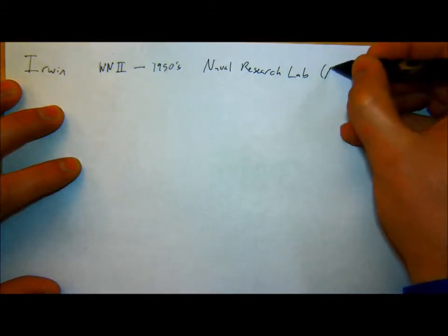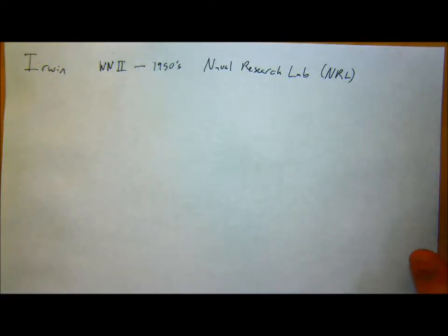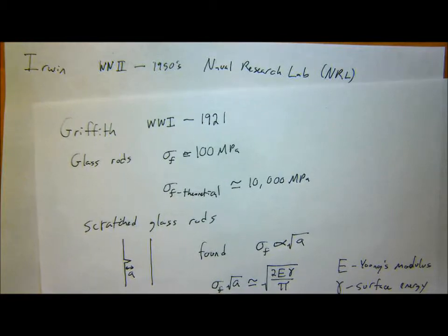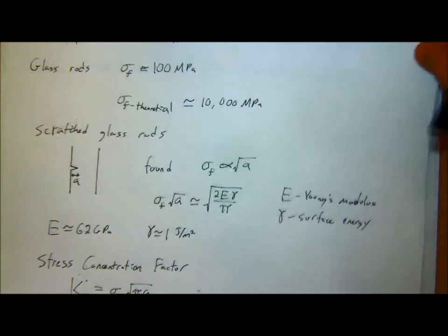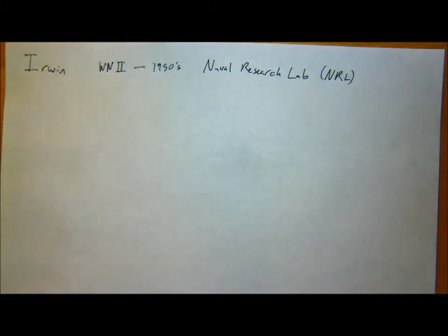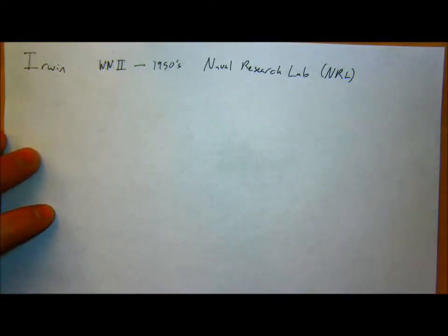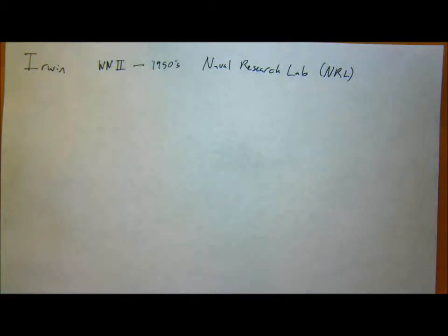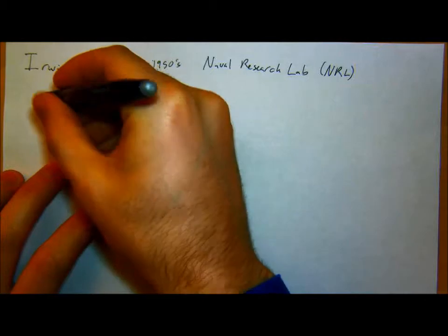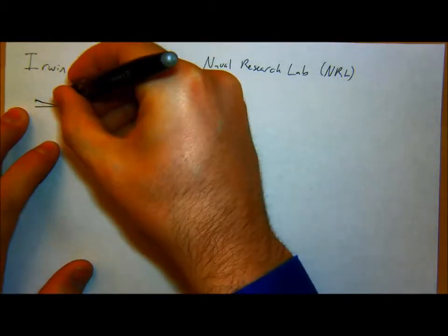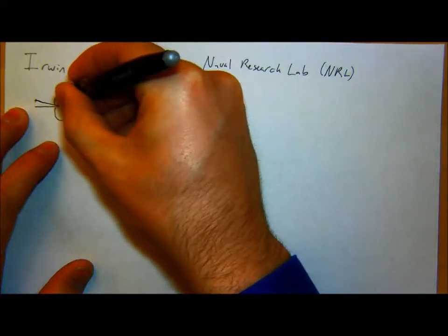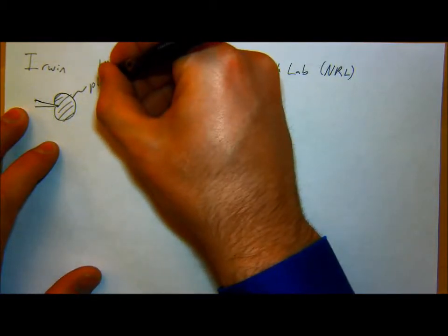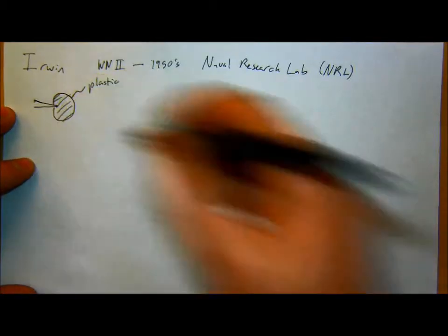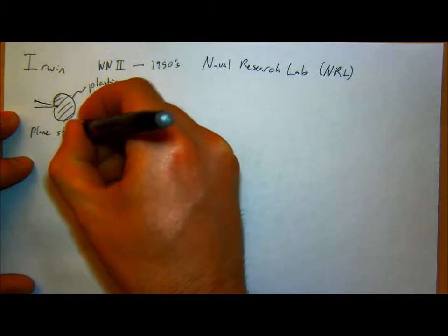Where Griffith was only thinking about glass rods, which are brittle materials, it turns out this relationship didn't really work as well when you tried to plug in values for things like metals or polymers, things that were ductile. So Irwin said, well, let's think about the plasticity around a crack tip. I know that I'm never going to get an atomically sharp crack in a material. Really, that crack is going to blunt out. So instead of just looking at the crack itself, I'm going to think about the plastic field around the edge of that tip. This would be for plane stress. It looks something like that, which again, remember, is a thin sheet. Or for a different shape, something kind of like this.